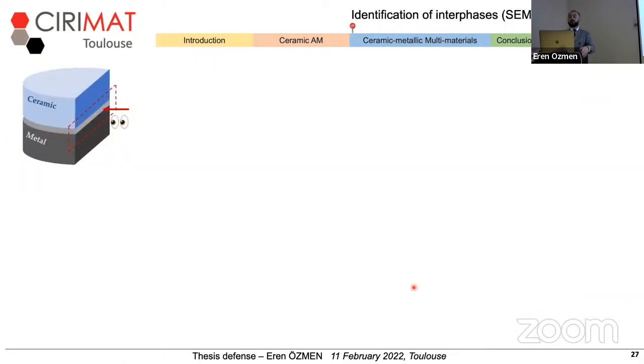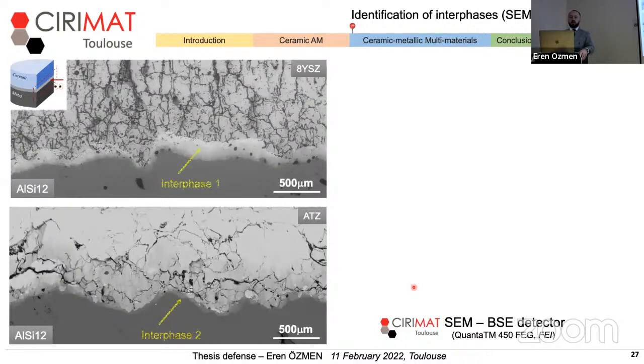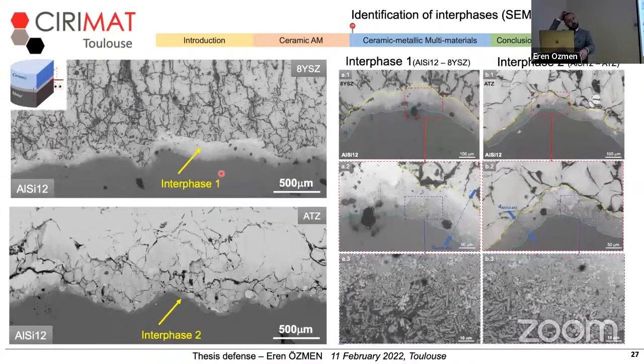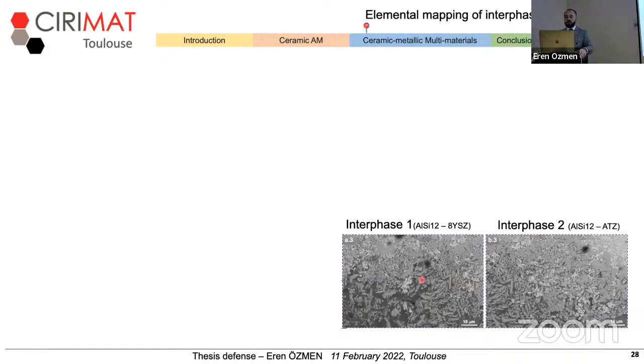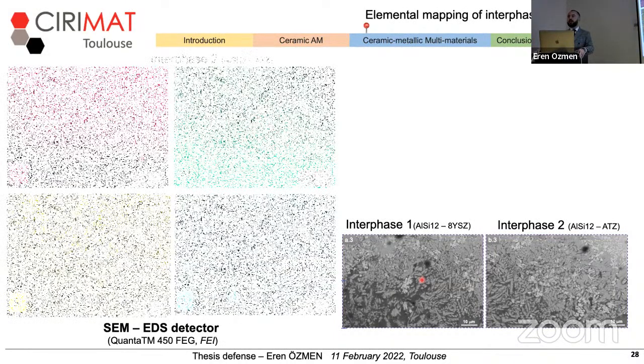To answer that, I take a vertical cross-section of the multimaterials, and when I observe them with scanning electron microscopy, I observe 2 interfaces for 2 multimaterials. And then with higher magnifications, we see that the borders of these 2 interfaces are quite easy to separate from the rest of the ceramic and metallic parts. And when we come closer, we see that there is grading in this microstructure. So at the highest microstructure imaging, I see that this microstructure is completely different from the ceramic and metallic part itself.